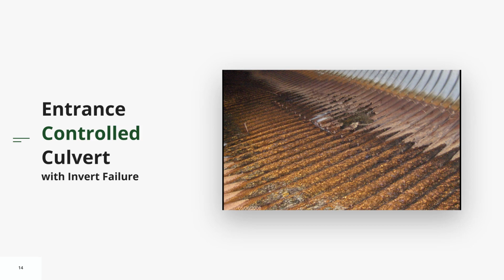And then what happens is that the bedding on the outside tends to get inside. The bedding around the corrugated steel pipe is like the concrete in a normal beam. It's the compression part of the structure, whereas the corrugated steel is the tensile part of the structure. Concrete is the compression part of a beam, whereas the rebar is the tensile part of the beam. Well, here, if you lose your gravels on the outside of the pipe, then you've lost your compression part, and if you lose that, you lose the structure. So you get a failure of the pipe.